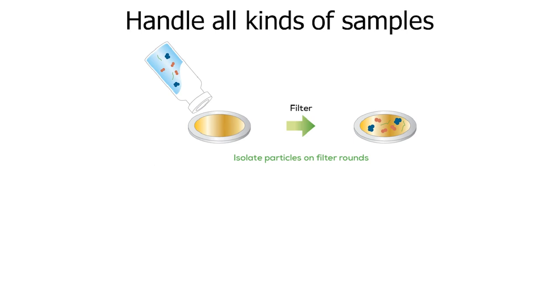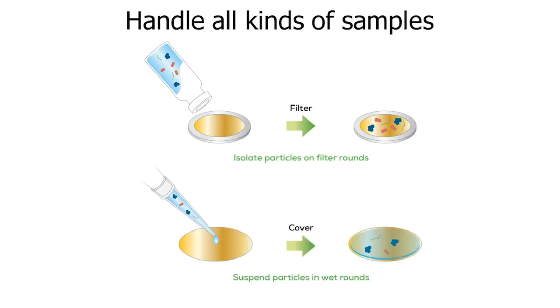Sometimes, though, you have particles in suspension and you want to keep it that way. Whether it's because your particles are amorphous or another reason, the liquid suspension can simply be pipetted onto a gold-coated wet round and analyzed directly.